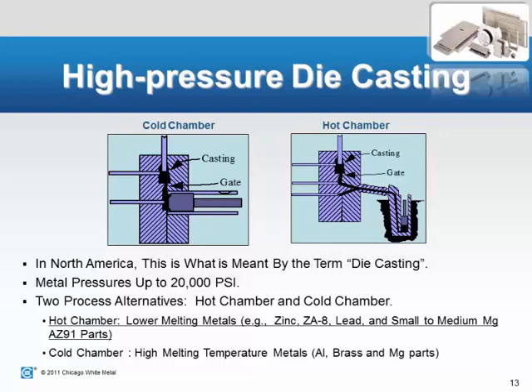In our process, in the high pressure die casting process, the metal pressures can get up to about 20,000 psi. So when we inject the metal into the die, it's extremely high pressure, and that's what allows us to get the thin walls and the features as cast in net shape as we can. So that's kind of why that lends itself.